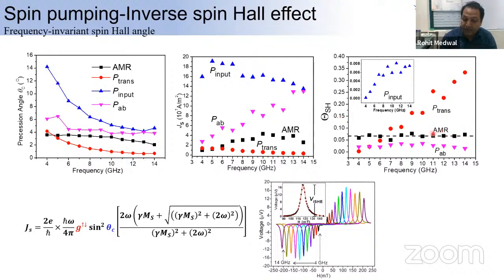Generally people were trying to report the spin Hall angle for a lower range of frequencies, and then say this is the percentage of the spin Hall angle. But you can see that if people are reporting from the power transmission, they can say the spin to charge conversion in the platinum is 30%, where others can say this is 10%. But ideally, theoretically, it is 5 to 7%. And we have successfully demonstrated that the frequency invariant spin Hall angle in the platinum using the AMR is around the same as what has been predicted theoretically. This was the first discovery.